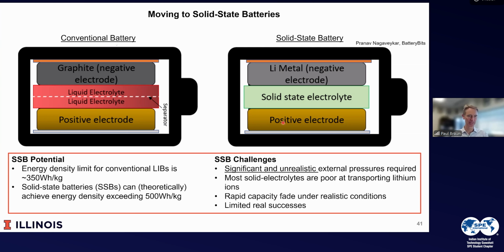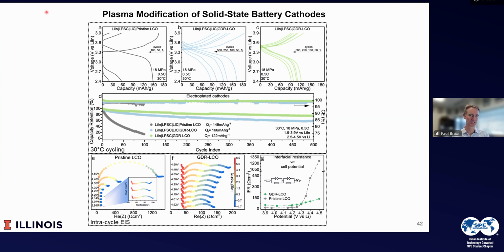And so what we wanted to see is, would the plasma process provide advantages? And indeed, we see it does. So if we make a battery here, the key to look at is it's just pristine LCO. So this is our electroplated LCO, and it is facing lithium indium chloride. And this is the one with the plasma treatment on the surface with lithium indium chloride. And then finally, here's one with LPSC. LPSC is not thermodynamically stable, so without treatment, it simply dies. And what we see is that if we don't treat the cell, it dies within 20 cycles. When we do treat the cell, it cycles out past 500 cycles.